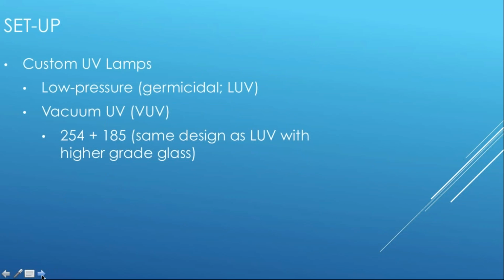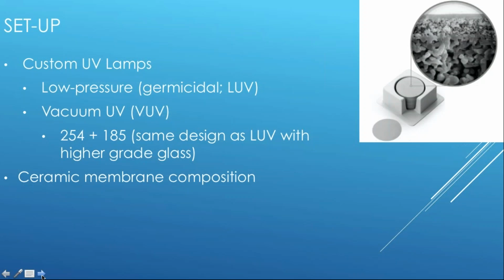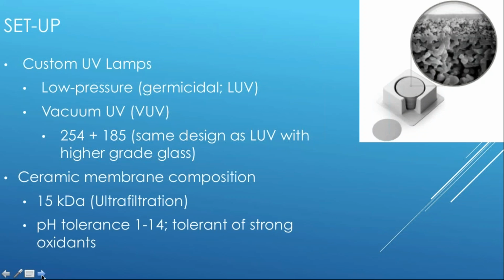The initial setup was we had multiple types of lamps. So we had a low pressure UV, and we had a vacuum UV lamp, and initially we only had ceramic membranes. These were just 47 millimeter in diameter disc membranes. They were composed primarily of titanium dioxide. They were 15 kilodaltons, and with ceramic membranes, you have large pH tolerances, and they can pretty much tolerate any kind of chemical you can throw at them in terms of oxidants.